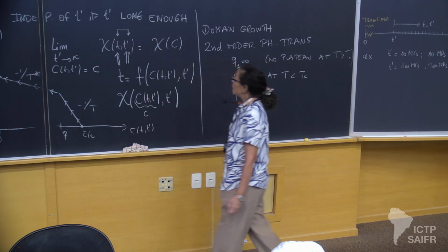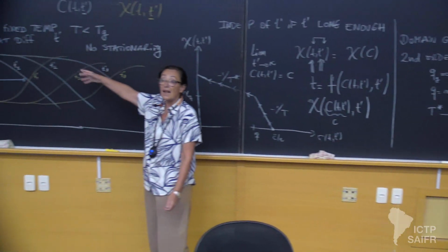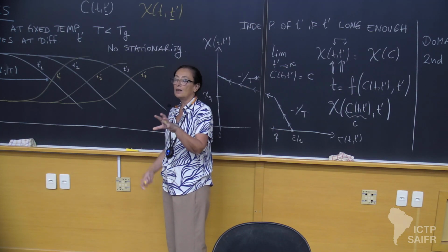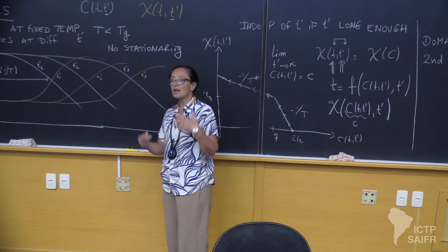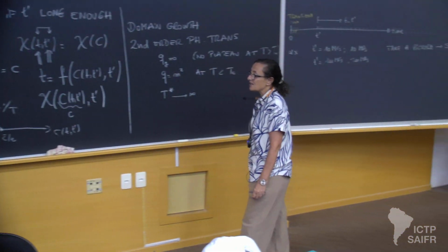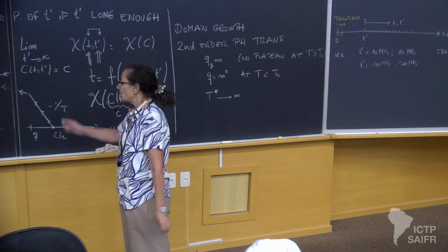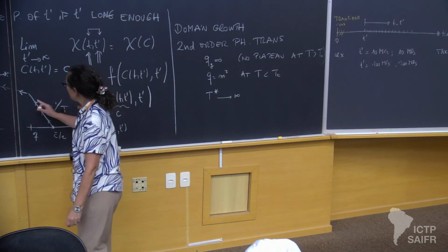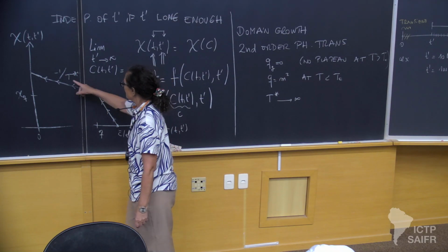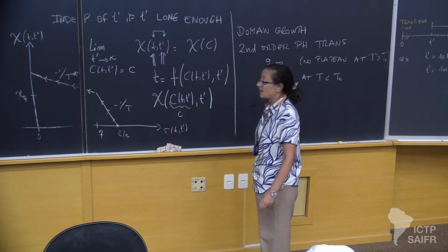Fine? Okay, so this broken line is what is observed in different kinds of models of glasses, mean field, but also in molecular dynamics simulations of Lennard-Jones mixtures, hard spheres, different kinds of models that have a glassy transition and a low temperature glassy phase with non-equilibrium relaxations and violations of the fluctuation dissipation theorem. But you see, in a form which is not very complicated. This part is controlled by the temperature of the bath, as I was saying yesterday, and this part is controlled by a self-generated internal temperature in the sample.